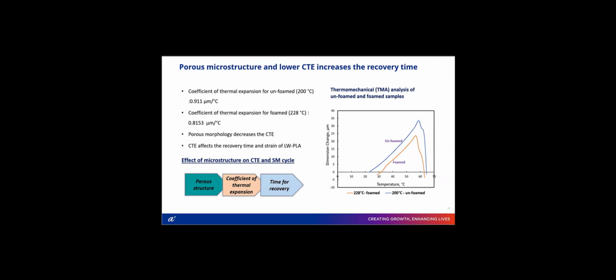One possible explanation for the longer recovery time of the foamed sample is the coefficient of thermal expansion. We analyzed the lightweight PLA with thermomechanical analysis. For the foamed and unformed samples, you can see from the graph that the foamed sample has a lower CTE than the unformed samples. This may be because the pore structure acts like an insulator, which decreases the coefficient of thermal expansion and affects the recovery time as well as the recovery strain of the lightweight PLA.